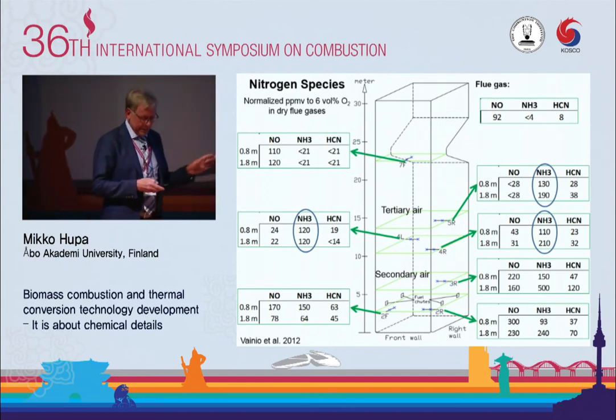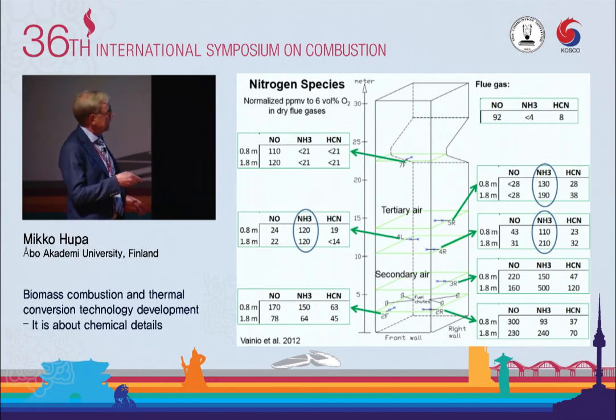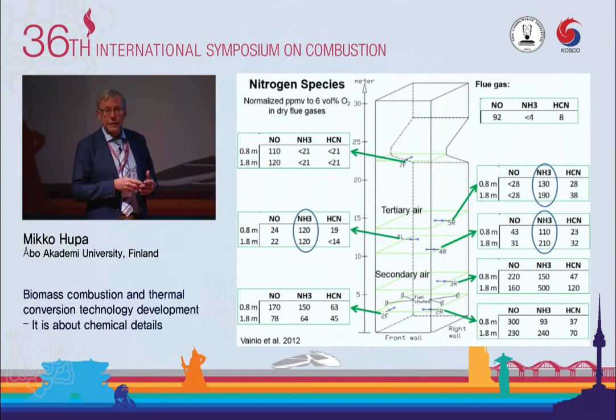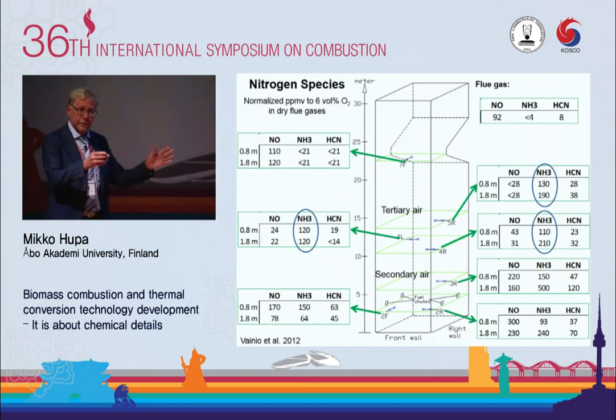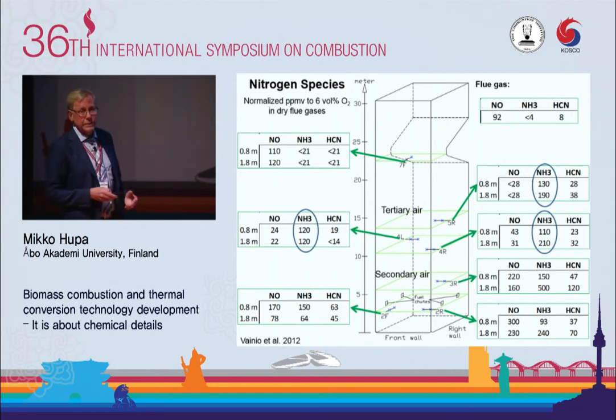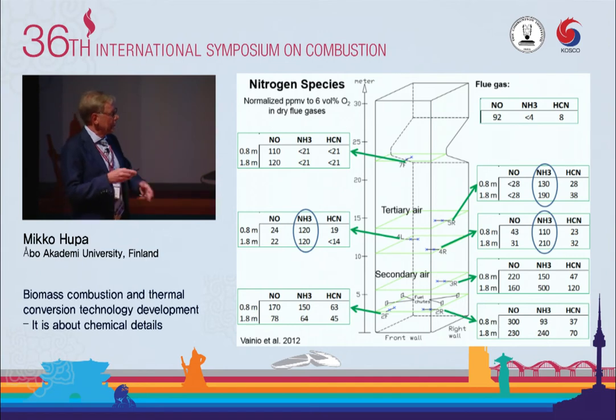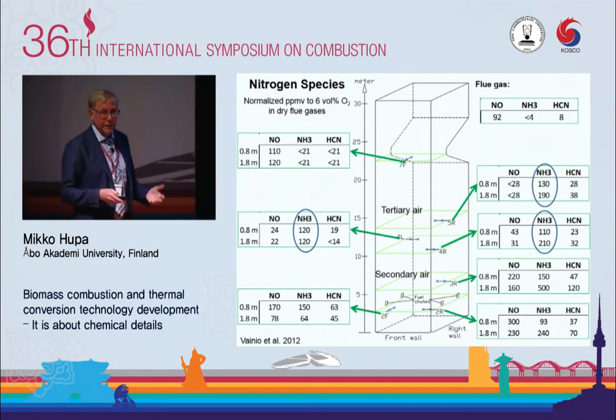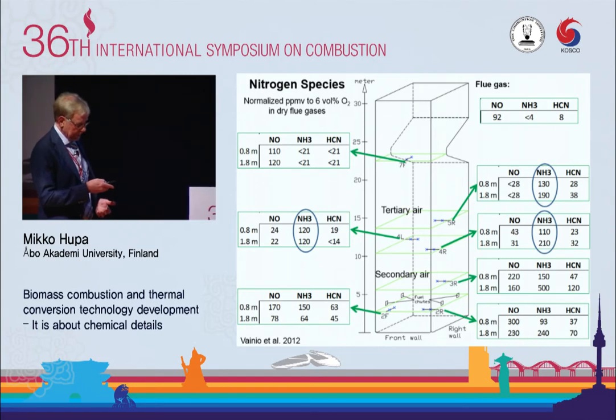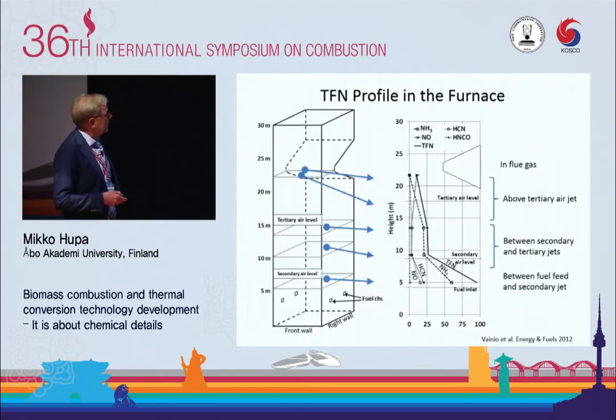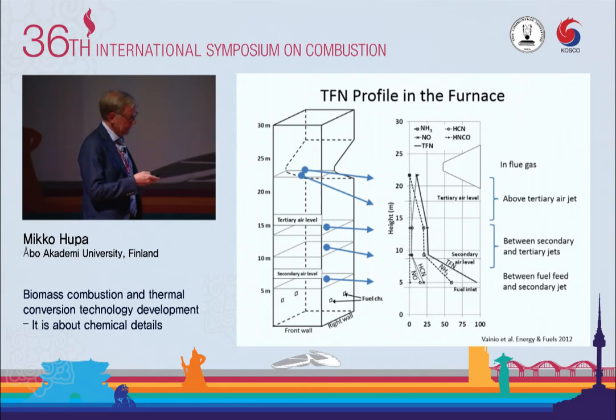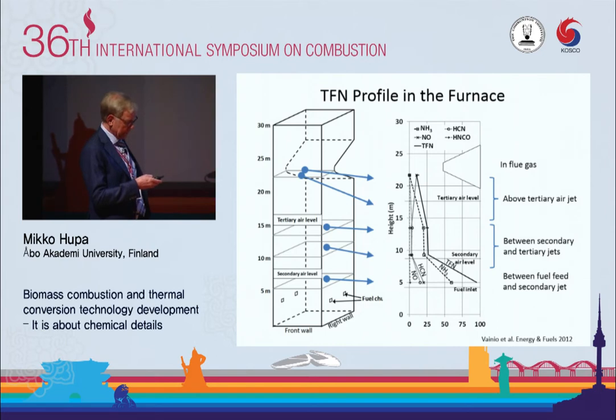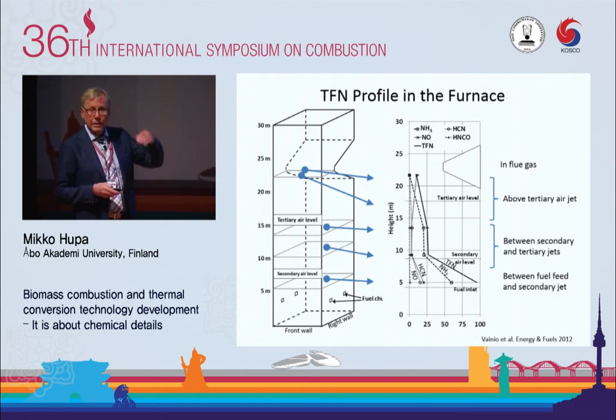There were a couple of interesting details here which we focused on. One was that we did find relatively large amounts of hydrogen cyanide, which we didn't expect, because in laboratory tests or in tunnel furnaces, you don't detect so much hydrogen cyanide for biomasses. It's almost all ammonia. But here, obviously, we have a chemistry in the lower furnace where some hydrogen cyanide is also produced.